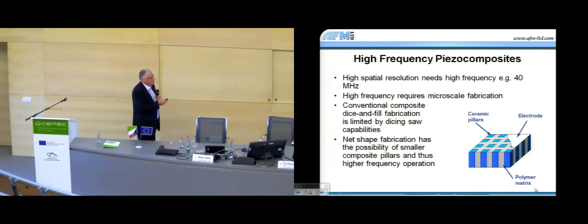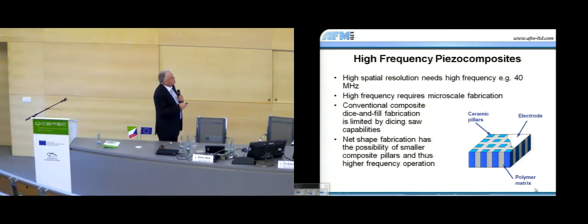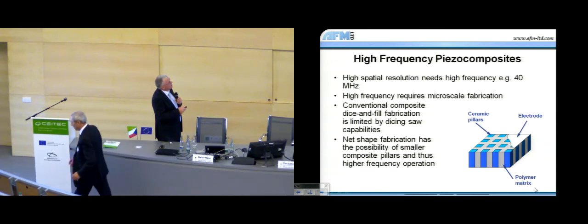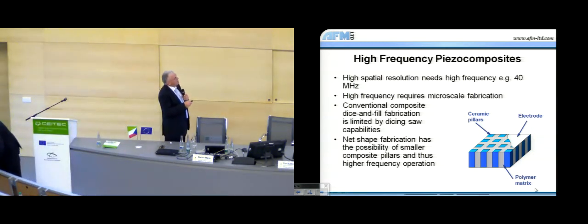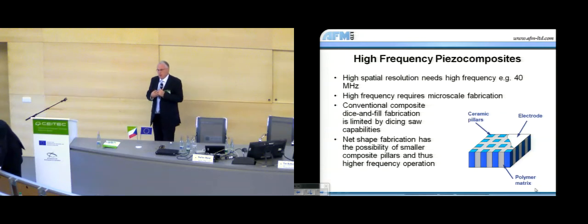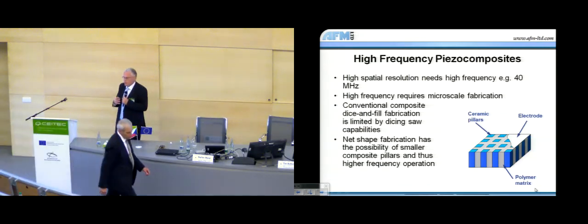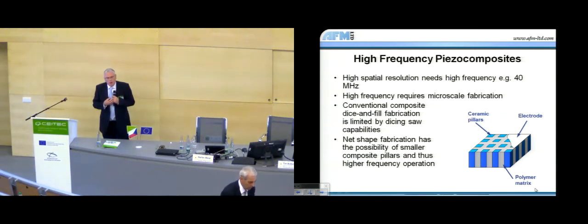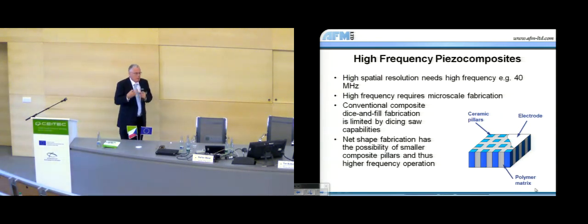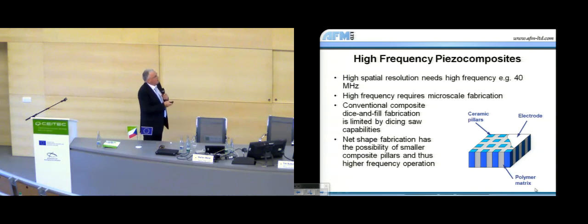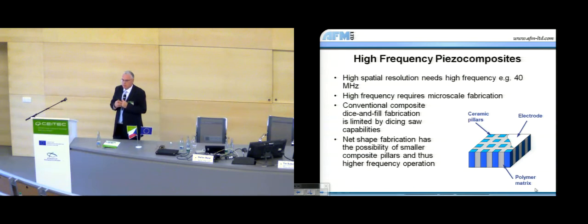So something that I might be interested in. And this is a typical structure that one wants. So pillars of piezoelectric within, in this case, a polymer matrix with an electrode on the surface. At lower frequencies, you can make this device by machining. At higher frequencies, then really the brittleness of the ceramic and the size of the elements that you want to make comes down to 10, 20 microns or so. This gap becomes less than 10 microns. It becomes very difficult, if not impossible, to machine.